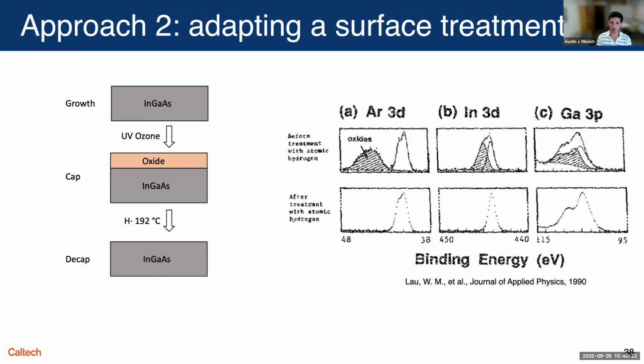So this is a plot of XPS data before and after that atomic hydrogen treatment. And if you look at the shaded regions in the upper plot, those are basically due to the elements bonding with oxygen. And if you look in the bottom plot, all those shaded regions are gone, which is interpreted as the atomic hydrogen removed the oxide. And this has been very successful for enabling a nice pristine surface to grow another film on top.